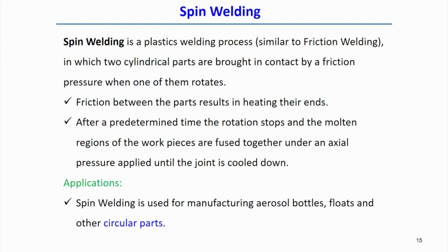It is a similar principle to friction welding processes, in which two cylindrical parts are brought into contact and joined by friction pressure, and definitely one of them should rotate, that means there is some relative rotational velocity between the components. Friction between the parts generates the heat, and after a predetermined time the rotation stops, and then the molten regions of the workpieces fuse together by application of an axial pressure until the joint is cooled down. So, we can keep on holding the axial pressure till the joint cools down to room temperature.